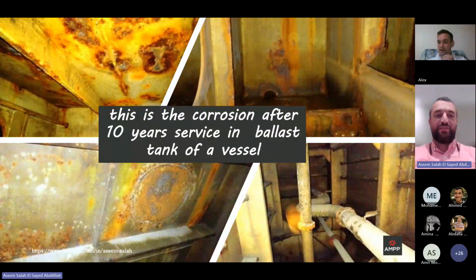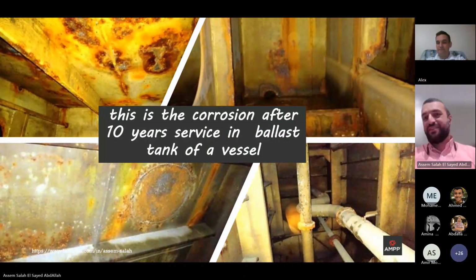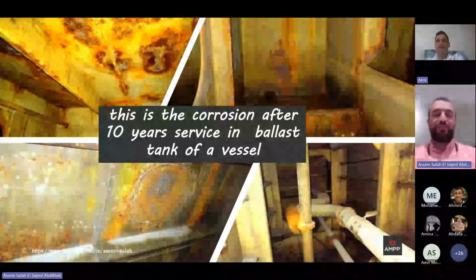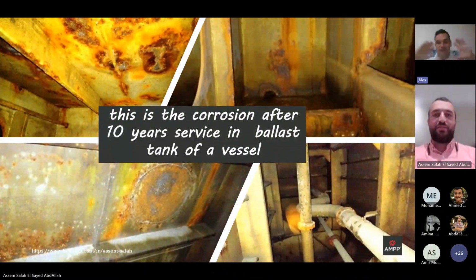So you are not willing to call it wet blasting. No, we would say high pressure washing. It's 500 bar. Washing, yes. It will not remove the rust itself, but only remove the loosened paint, the paint which is badly adhered, and then they repaint with 2 coats. It's not very effective, because in the next photos, if you slide, Asim, please slide to the next photos.